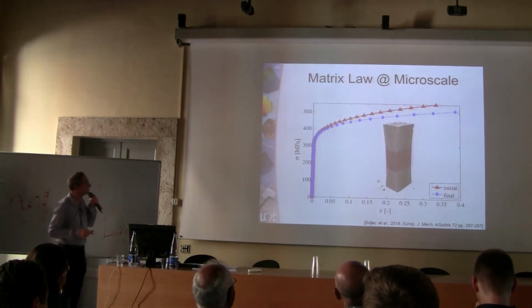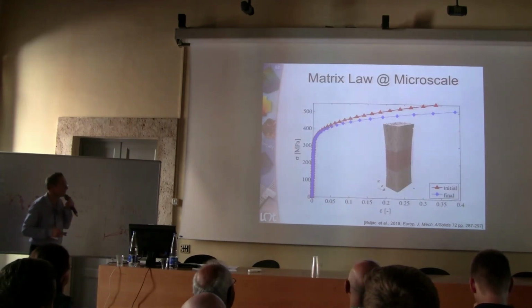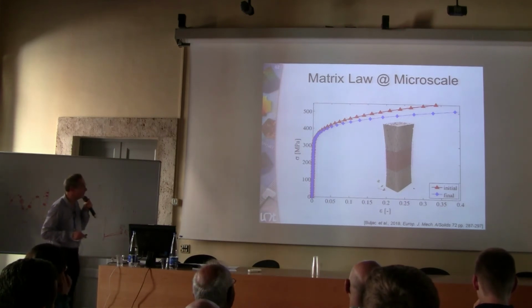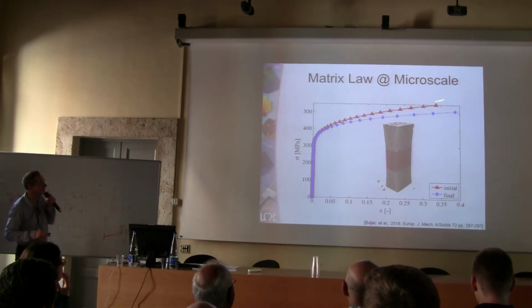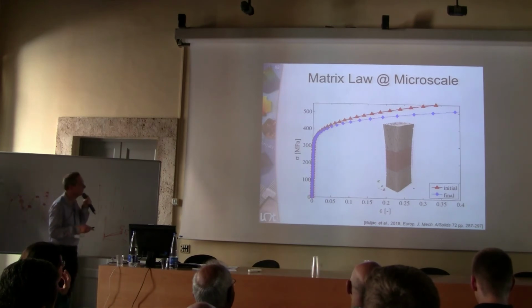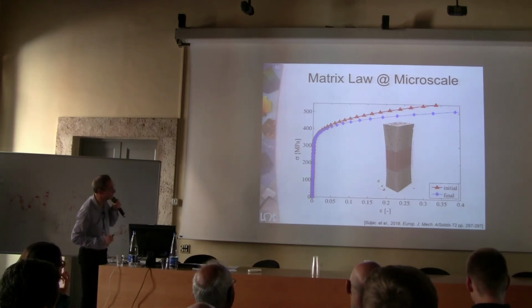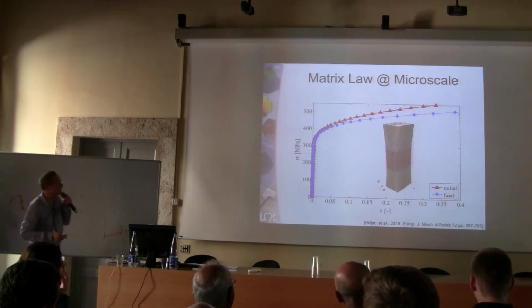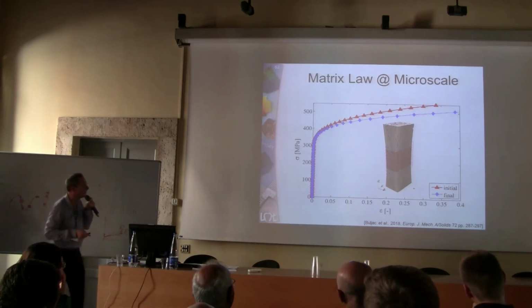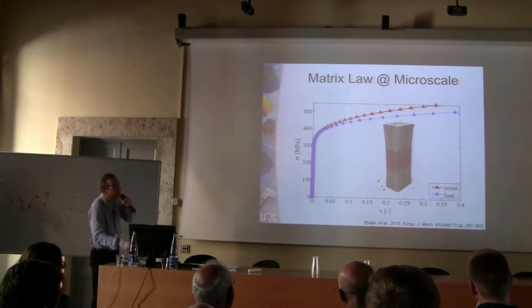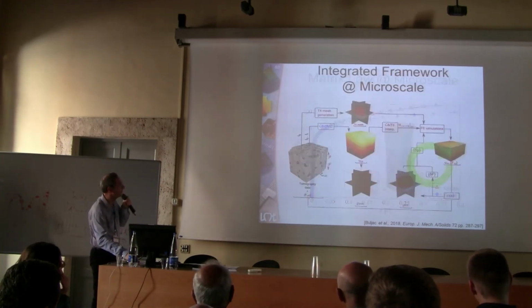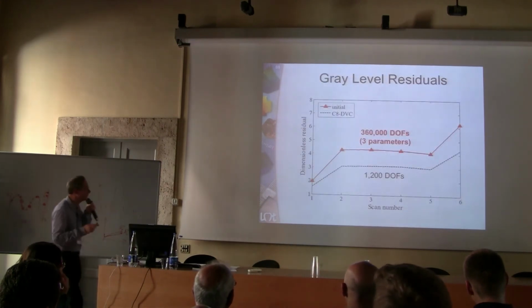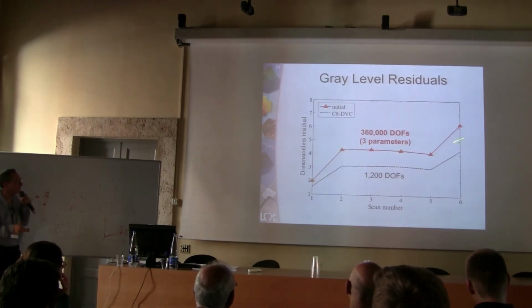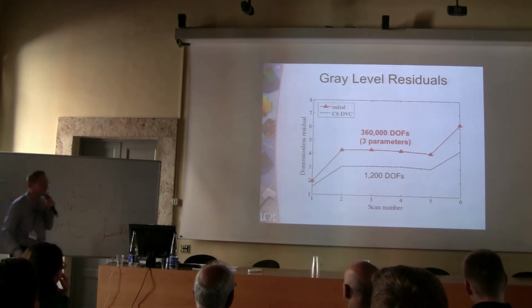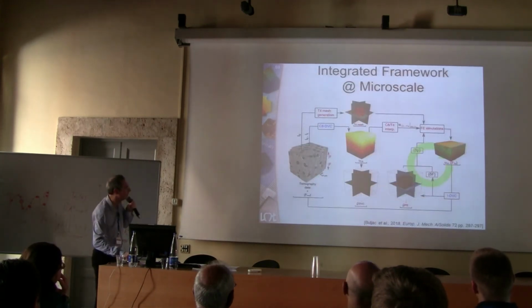And here is the result for the stress-strain response of the ferritic matrix. So the initial guess was basically obtained from literature data, and the final result shows you that most of the difference comes in, no surprise, in plasticity. But still, we won't be able to predict what's going on here, and what was going on here was coalescence. But that's another story. Okay.